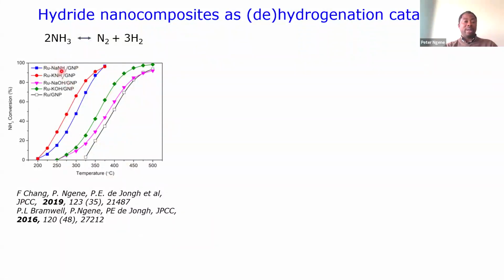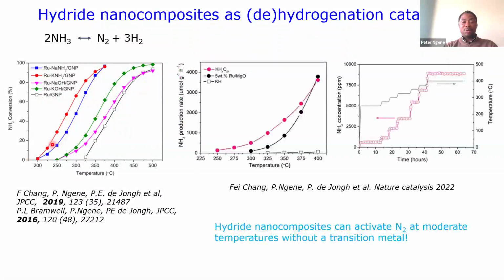And this is just one of the works we did in time past to show that these metal hydrides, here we're looking at sodium hydride that we confined inside graphene nanoplates, which is just nanoplatelet graphite. What we can see when we compare this material is the amount of ammonia that is converted as a function of temperature. Now, the classical catalyst that is used to do this is ruthenium. But we can see that when we add this metal hydride, sodium amide, potassium amide, the activity, our ability to crack ammonia at moderate temperature, is much, much higher. So these metal hydrides are not only for hydrogen storage, but they also serve as a catalyst.